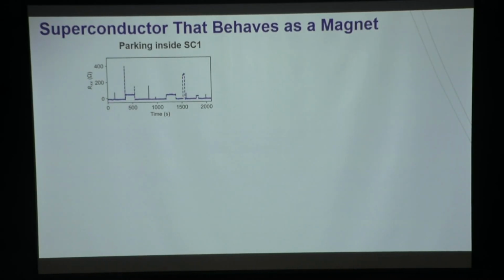We fix the top and the bottom gate voltage and just watch it as a function of time. Surprisingly, we found that this state, for most of the time, stays as zero resistance, or the superconducting state. But from time to time, it will deviate from zero shortly, or stay a little bit before going back. So this fluctuation that we saw in the previous map is not triggered by some gate voltage scanning. It is a temporal fluctuation. The superconductor itself will just do this, possibly due to some thermal radiation from the environment or coming from the